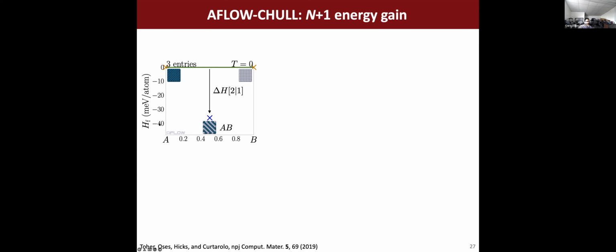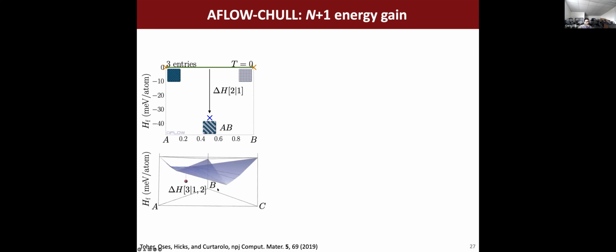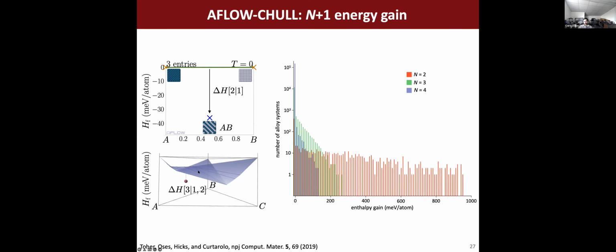And we can do this analysis even for higher dimensions. So now we have 3 components here. And for a particular ternary, we can ask, what is the energy gain from increasing the number of species from 2 to 3, or 1 or 2 to now 3 components. And we've done this analysis for all of the metals in the AFLOW database. And what we're showing here is the enthalpy gain distribution for the number of alloys for binaries, ternaries, and quaternaries.